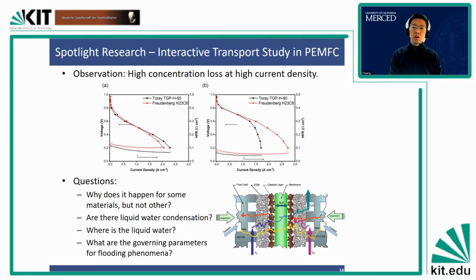But for the material that we put in the fuel cell stack to run durability, those materials are typically very robust in terms of their performance under both dry and wet condition. And the failure modes that we observe are either membrane degradation, either chemical degradation or membrane pinholes, or catalyst degradation. It's like loss of ECSA, loss of its activity, or platinum dissolution, carbon corrosion. These are more of a significant issue in durability study rather than the diffusion media, because like I said, we don't purposely put a diffusion media that will cause flooding and then run durability test.